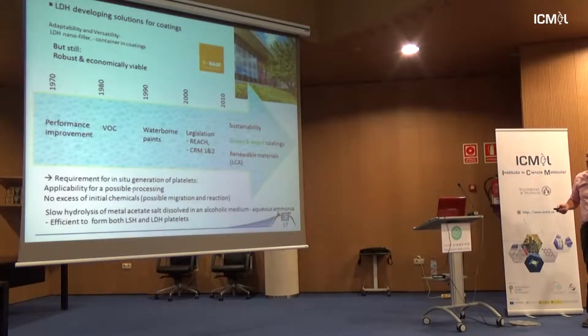So what we decided, because we work on different solutions, was to try to generate in situ platelets directly inside the polymer coatings. That would be a zero chemical impact, directly forming the LDH in the polymer. But of course, with no excess of initial chemicals, so everything put inside has to react. And you have to find a good process, as we were talking about earlier.